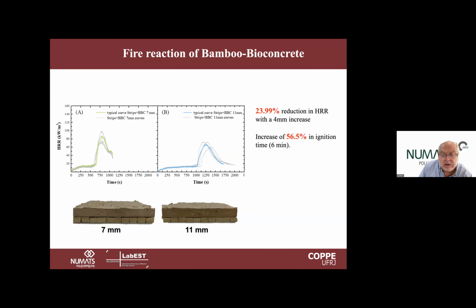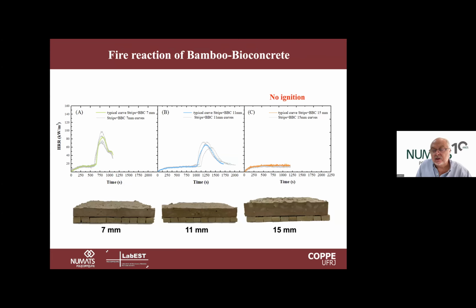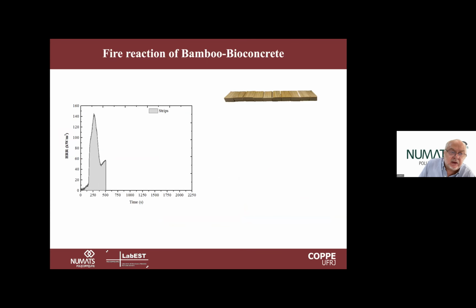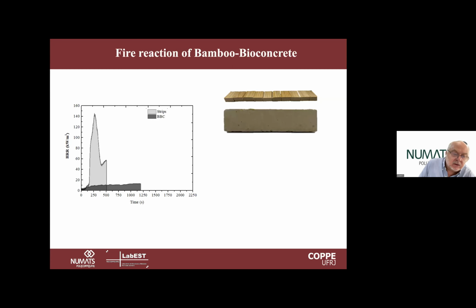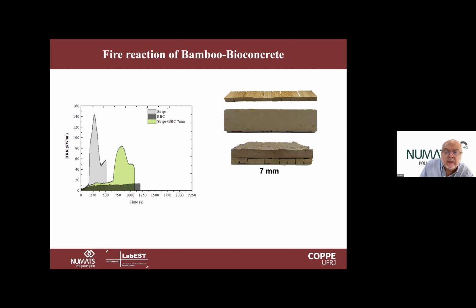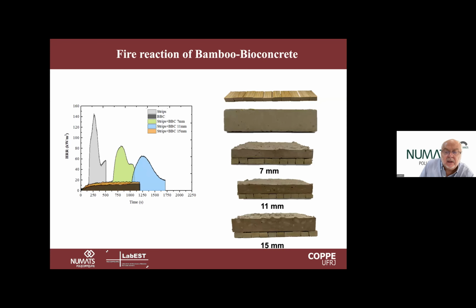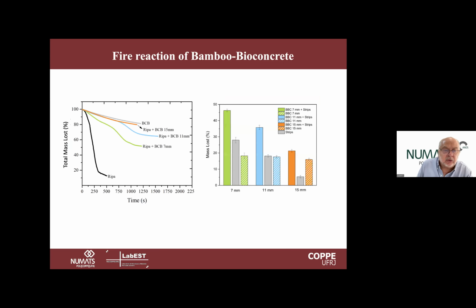So 7 and 11 millimeters is not enough to protect the bamboo completely against ignition. But with 15 millimeters, it's very much the same behavior as the bamboo bioconcrete. So we see here with this strip the heat release is very fast, so the process is quite quick. And then with bamboo it's low, and then 7 millimeter, 11, and 15. With 15, we come back nearly to the same situation where we have no strips of bamboo. So protection is total. Here we see the total mass loss.